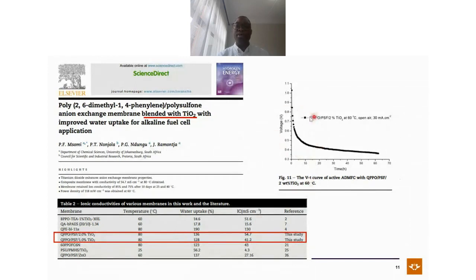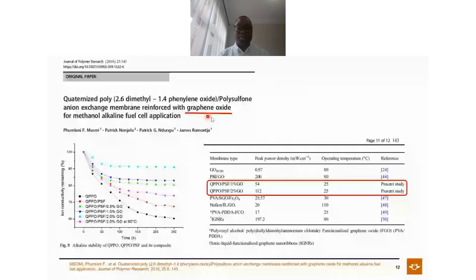We also did what you call a voltage curve. This basically tells you, if you have an open voltage and you're running over time, how much degradation will happen in terms of your open circuit. So basically, if you look at here, this was our OCV. It started at about 1. When we leave it for about 60 hours, we can see that it degrades, but it still retains about 0.3. And this was also one of the highest when you compare. Some materials, after a few hours, go to 0, which means the fuel cell is not functional. So ours was functional.